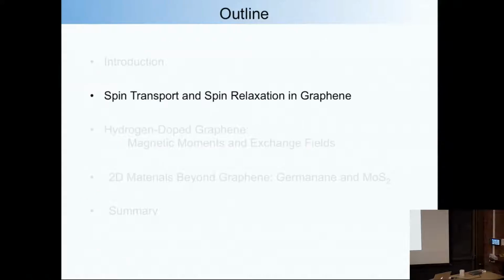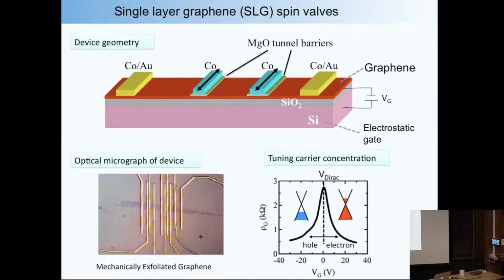Okay. So I want to tell you about the experiments that we're doing on spin transport, and I'm not assuming people are familiar with this. So it's a little bit pedagogical, but it is a little bit different than magnetoresistance measurements that are typically done in spintronics. So the device geometry is we have this red strip, which is graphene, and we put on magnetic electrodes. They're going to serve as spin injectors and spin detectors, and sometimes we have tunnel barriers, sometimes we don't. That looks almost as easy as theory. I know, done by PowerPoint.